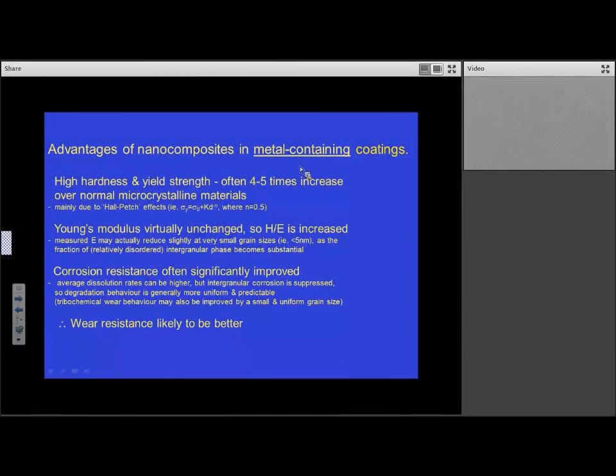So that's a layered structure, but why are nanocomposites even better? Well, a number of reasons. With nanocomposites we can get so-called Hall-Petch hardening. We can get grain size induced hardening. We can retain the elastic modulus of the metallic species in that composite. And there is a further benefit, and that is that the corrosion rates are more uniform. Intergranular corrosion is suppressed, and so degradation is more uniform and predictable. We don't get localized pitting corrosion. So overall, with a nanocomposite, we get an enhancement of H over E, and we get good corrosion resistance and better wear resistance overall.